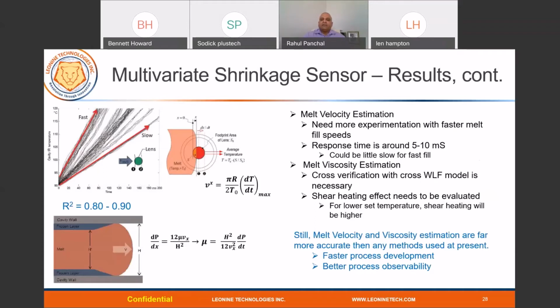Especially for melt velocity, we think the response time is not as fast as we would like for the faster injection speed. When the injection speed is above 3 inches per second, or 75 or 80 millimeters per second, it's not fast enough. Below that speed, it is enough. Same with the melt viscosity estimation, it is pretty accurate.